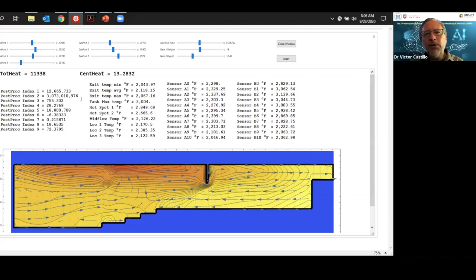And then additionally, after they run the simulations, the CFD, they run thousands of tracers through there, and these tracers mimic the flow path of the raw materials. From that, they can get post-processed calculations based on the distribution of what these particles are seeing, what kind of heat flows they're seeing, are they being overcooked or undercooked? And then they produce these post-processing indices that are the simulation predictions of the quality, the quality indices. And we can match that up with production plant flaw data, and I'll show that in a second. And so if I go back to